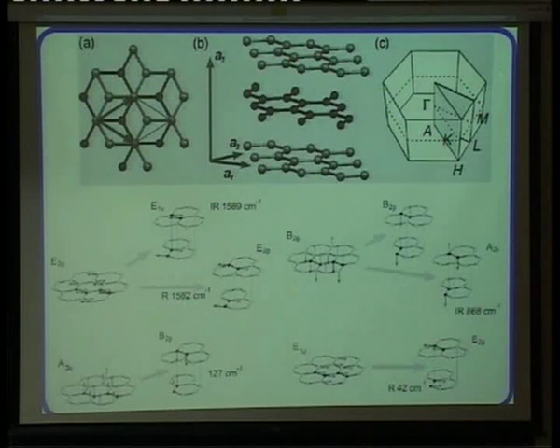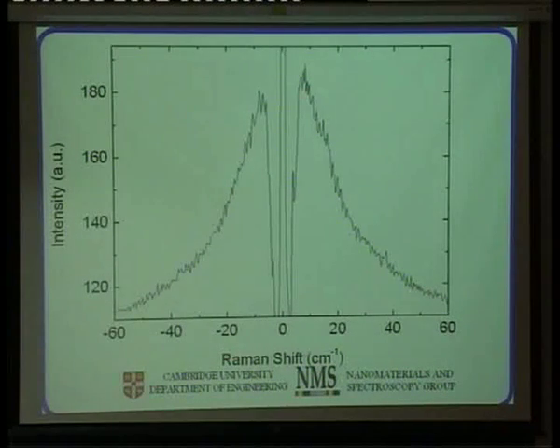It's interesting also for people who care about electrons, because the electrons are crucial in the Raman process, as I mentioned before. However, this particular phonon is due to the relative motion of 2 planes. So this phonon actually cares if there is 1 layer, 2 layers, or 20 layers, and is a phonon that directly probes the number of layers in the sample. The problem is that the frequency is very small, 42 centimeters minus 1.